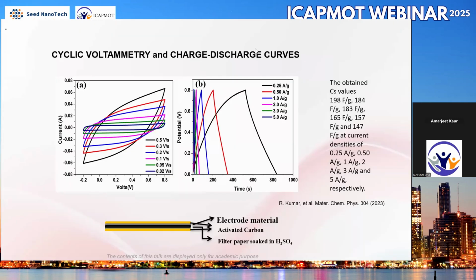So this is our device configuration as shown here. We have the electrode material on which we have deposited the activated carbon, and then we have a filter paper with sulfuric acid as the electrolyte. Initially we do the cyclic voltammetry. For the initial voltage rate, we are getting almost a rectangular shape, which is the characteristic of any capacitor showing the maximum charge storage. But gradually you can see that this is deviating away from the square shape because of diffusive ion transport. This is the reason for getting these kinds of shapes.